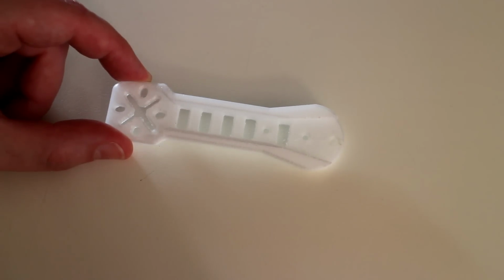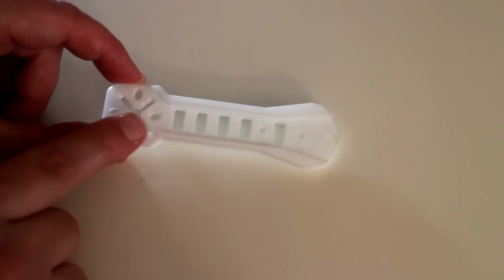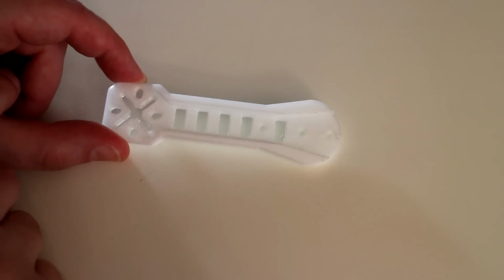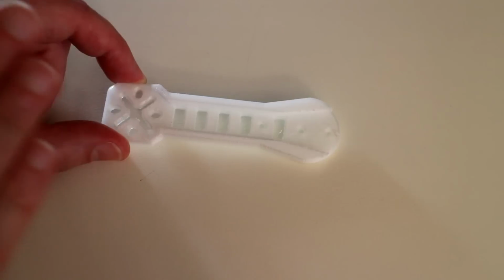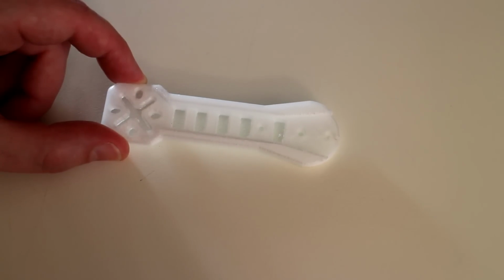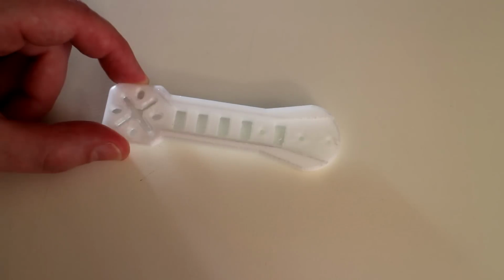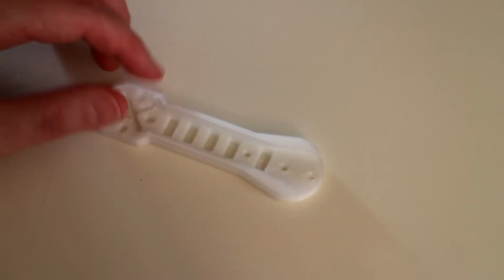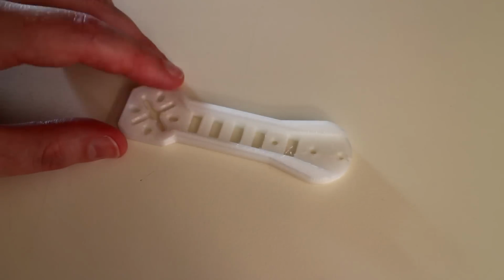And also, I had the retraction settings quite aggressive. I was retracting at 3 millimeters at 150 millimeters a second, and it was still oozing. Those settings are my go-to settings for other filaments, and it seems to mitigate any oozing, but it didn't with this nylon bridge, so that was disappointing to see.